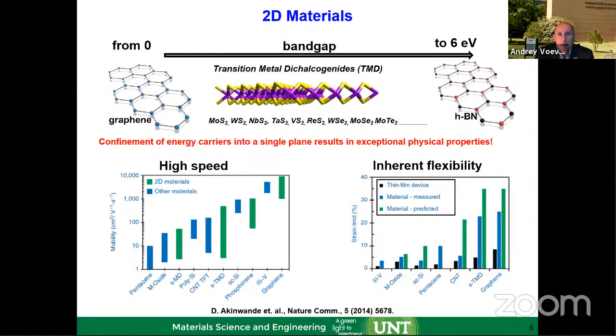One of the very dominant groups is the dichalcogenides. Dichalcogenides consist of metal atoms with sulfur or selenium atoms attached on the top and bottom here, but it's still one monolayer, because within this group we have strong covalent bonding, and outside there is almost no bonding, which again gives us very interesting properties of confinement. But now we can confine both electrons and holes and make N-type and P-type semiconductors. And because they're very thin, they give us a very interesting property, a direct band gap, leading to photovoltaics and basically solar-to-energy light conversion.